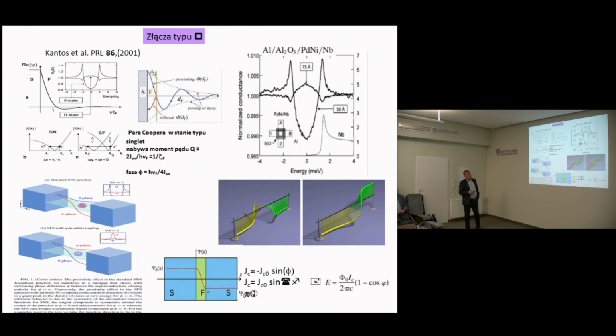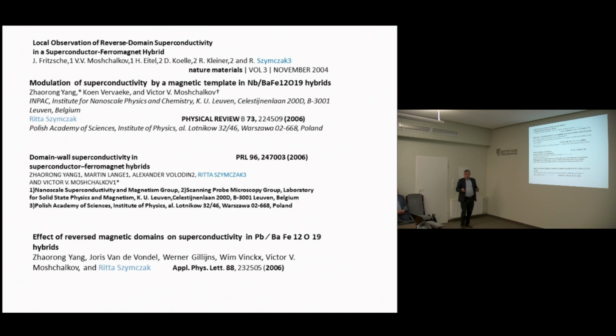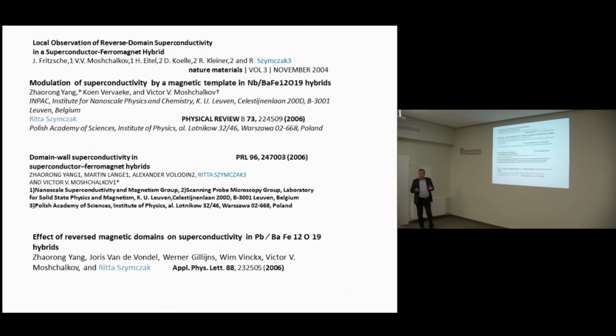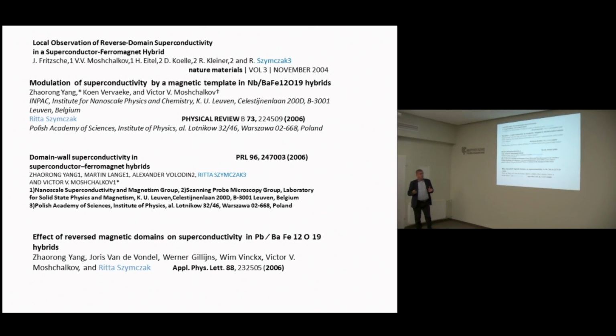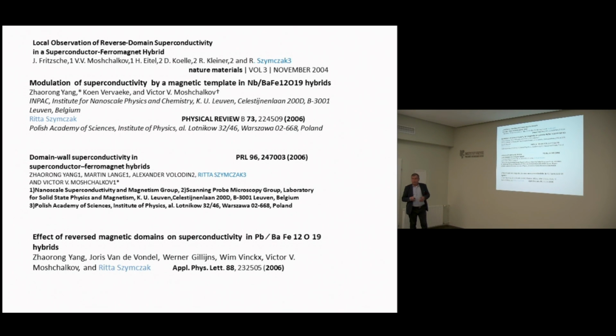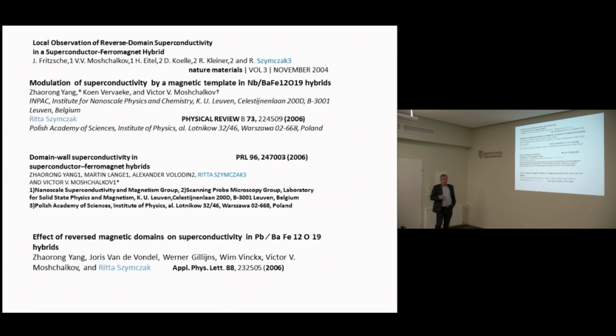This was demonstrated experimentally by Kontos, where, of course, they used diluted nickel palladium as a ferromagnet, and as we see, we observe this type of behavior. And because of this relation, this should be phi plus pi, that's why it's called a pi junction. I mean, there are, of course, many more different kinds of phenomena occurring at ferromagnet superconductor interfaces. For example, if we have a superconductor ferromagnet superconductor structure with a non-homogeneous ferromagnet, we can induce a triplet state. These are phenomena related with the proximity effect.